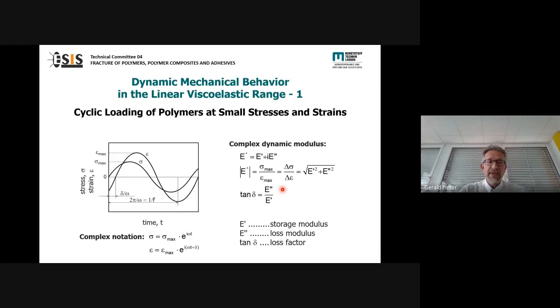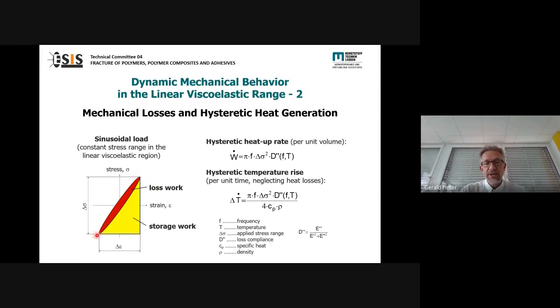If we now plot stress over strain as a function of cycle number, we typically measure in viscoelastic polymers a hysteresis, as you can see here: stress over strain, and here the hysteresis. The loss work, so the work that cannot be recovered, is the area within the hysteresis. And we have the recoverable work, that is the yellow area below the hysteresis. As a result of the lost energy in a fatigue test, we have to deal with hysteretic heat-up of the polymer and of the specimen. This also has to be considered if you are doing a fatigue test.